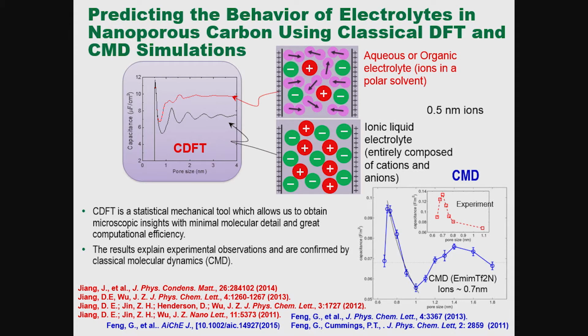We've done a lot of computational modeling of slit pores and how electrolytes and ions enter and leave those pores. Ionic liquid-like simulated liquids tend to form first this anomalous capacitance at about one pore diameter, so a slit width about the size of the ions gives an anomalously high capacitance. Then there's a trough, another capacitance peak, and this is indicative of the layering of the electrolytes within the pore. Whereas the same ions dissolved in a simulated dielectric medium give this first capacitance max but then decay to kind of a uniform capacitance, which is actually higher for the same ion diameter behavior—and that's because the dipoles of the solvent are contributing to the overall capacitance. So orientation of these surface dipoles is contributing to the capacitive energy storage.